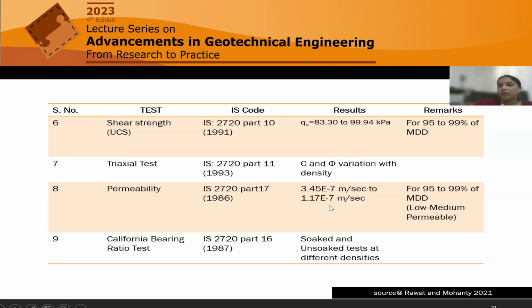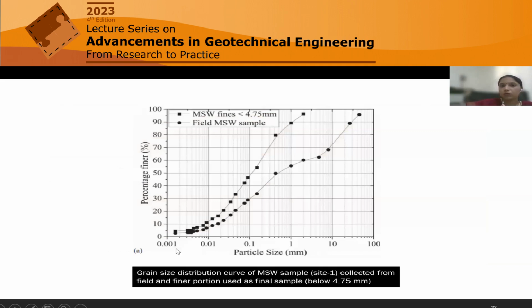Then permeability, the range is 10 to the power minus 7, 3.45 into 10 to the power minus 7, to 1.17 into 10 to the power minus 7 from 95 to 99% MDD, which is within the range of low to medium permeable material. CBR test we have also performed, both soaked and unsoaked. I will show you the result. This shows the grain size distribution curve for the field MSW sample. This one is the field raw sample, and this is the segregated finer than 4.75 millimeter soil-like material sample.